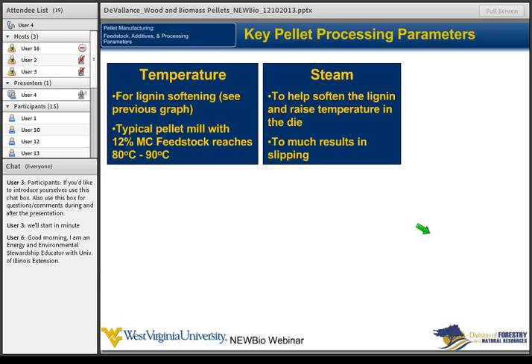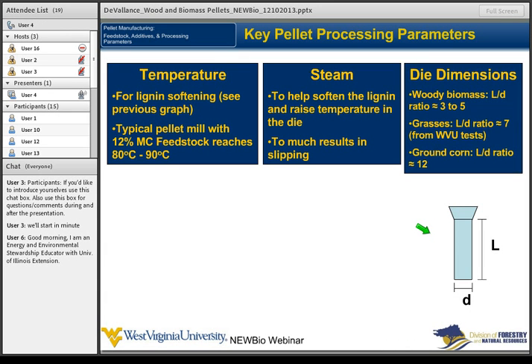You actually get a situation where none of the material is really flowing through the die well, and it builds up, and it can actually, at least I see this all the time in my case, stop the die from going around, and you build this big layer of non-pelletized material through there, and it's really hard to get anything to go through those dies.